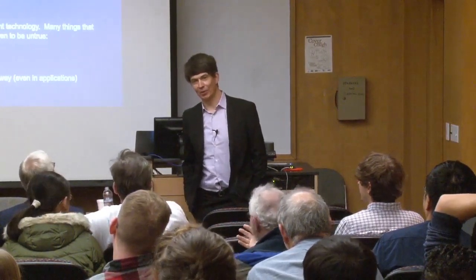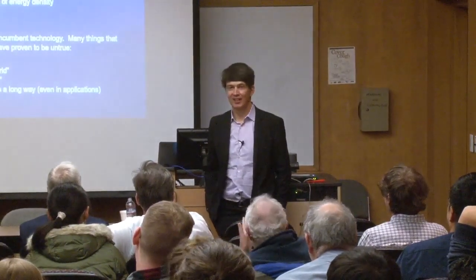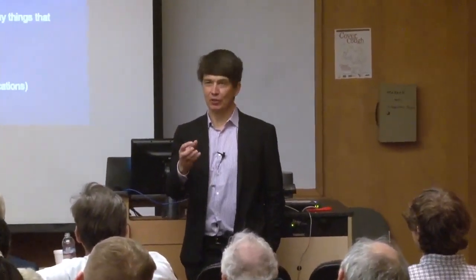More than we thought. When you start taking lithium out, you're doing two things, right? Obviously, you're creating a lot of vacant space, but then you're changing the valence state of the cobalt. You could think of it as p-doping, and obviously these materials become highly metastable. But you're operating at room temperature, so in principle the fact that they're metastable doesn't mean they will fall apart. We used to always think they would fall apart, but what we're actually finding is that these structures remain remarkably metastable, and it's not clear that structural stability in things like lithium cobalt oxide is the limitation to their operation.